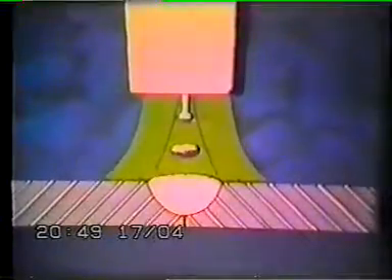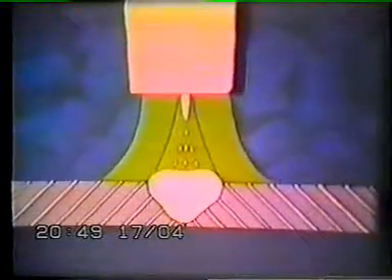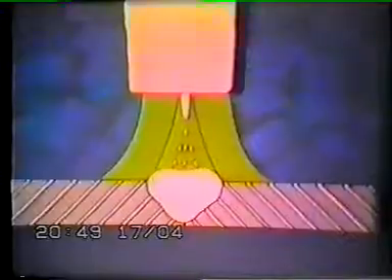In general, fillet and lap welding of aluminum requires more current than butt welding. But in both cases, if the current is too low, globular transfer takes place instead of the desired fine spray obtained at higher amperages. Another problem is burn back. To avoid it, make certain that the wire is level wound on the spool. Be sure that the drive rolls are adjusted to the right pressure. Apply enough pressure to the drive rollers so that the wire can be just held back by the operator's gloved hand.